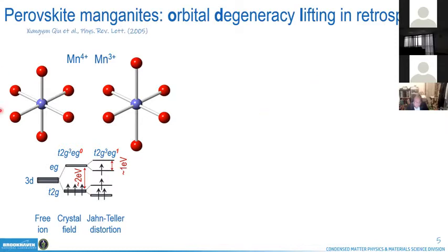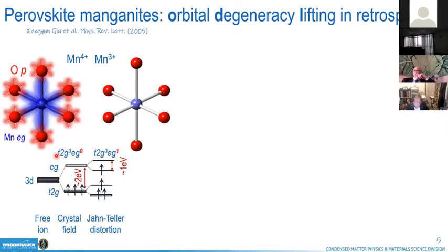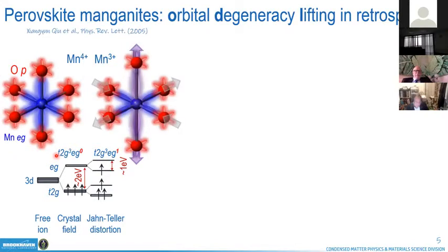The basic building blocks, and I'm sure all of you or most of you actually know about these systems or have actually studied them, in perovskite manganites are manganese oxygen octahedra. And manganese comes in different charge flavors. If manganese ion is free, it has a 3d sector completely degenerate. If you put it in an octahedral crystal field, it splits into eg and t2g manifolds. And then depending on filling and other interactions that I'm actually not going to mention, the orbital degeneracy is being lifted through the so-called Jahn-Teller effect, which actually involves lattice distortion.